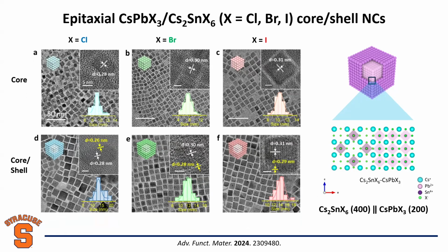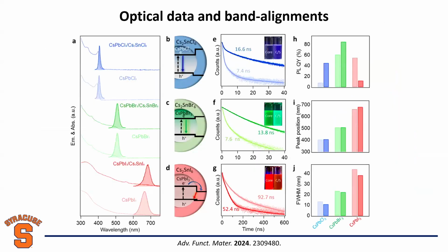Top row here is TEM of core nanocrystals. This is chloride, bromide, iodide, and the bottom is core-shell nanocrystals. You can see size usually increases from less than 10 nanometers to about 13 or 20 nanometers, a few nanometers, with uniform shell thickness. The higher resolution TEM can prove they have slightly different lattice parameters, but it is pretty solid. And depending on the halide composition, you can have different types of core-shell nanocrystals with different optical and electronic properties.